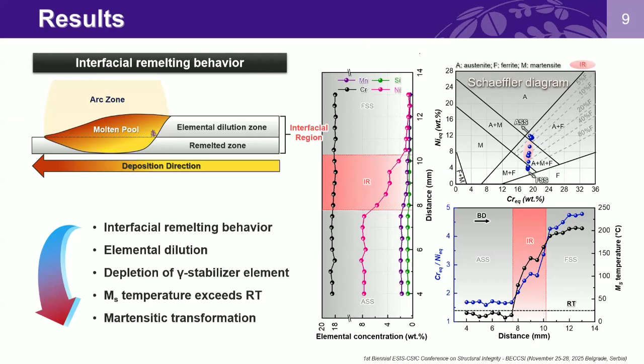As the schematic diagram shows, during the deposition of the ferritic stainless layer, the unsolidified austenitic stainless layer remelted as the arc passed through, enabling elemental dilution at the interfacial region. To analyze the elemental dilution behavior of the interfacial region, EDS line scans were carried out layer by layer along the building direction. It can be found that the elemental concentration of nickel reveals a stepwise decline across the interfacial region.